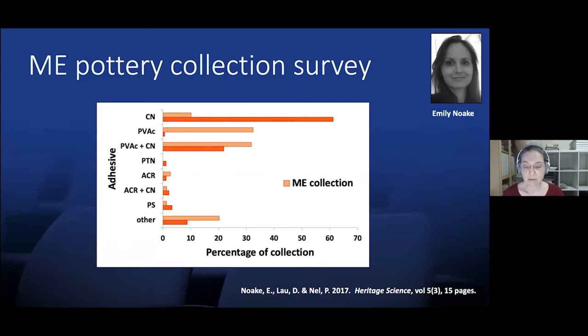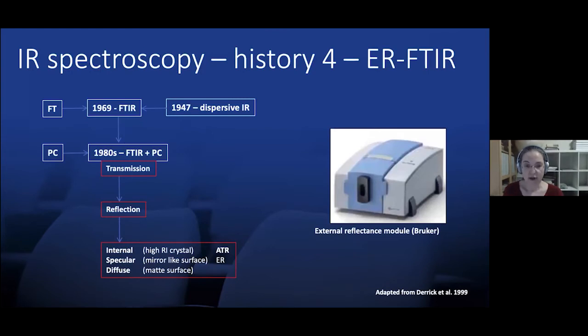Around this time, we became aware of another significant advance with infrared spectroscopy. In addition to the internal reflection or ATR sampling modules, there are two other types of reflection referred to as specular and diffuse. Bruker provided a sample module option referred to as the external reflectance module, where no contact whatsoever is required with the sample, and where the infrared spectrum obtained is a combination of both specular, highly reflective, and diffuse reflection from matte surfaces, and this is essentially dependent on the type of surface you're analysing.